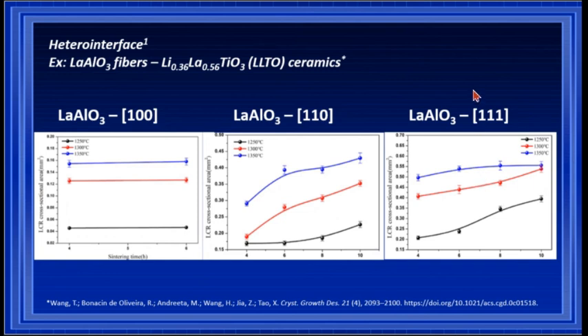We measured as well the effect of the crystallographic orientation of lanthanum aluminate fibers within the ceramics. So we used lanthanum aluminate fibers oriented in the 100, 110 and 111 directions, and analyzed the evolution with sintering temperature and time. We can see that for the 100 direction there is no evidence of an increase of the LCR region with sintering time, it's almost nothing. It doesn't grow any crystals considerably along the side of the fiber.